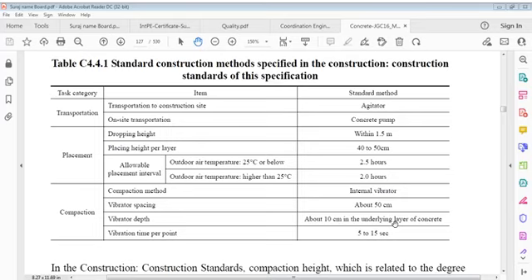Allowable placing interval: if outdoor air temperature is 25 degrees Celsius or below, it is 2.5 hours. Outdoor air temperature higher than 25 degrees Celsius, 2 hours. So if it is 25 or below, it is 2.5 hours, and if it is above 25 degrees Celsius, it is 2 hours. Compaction method: internal vibrator and vibrator spacing about 50 centimeters. Vibrator depth about 10 centimeter in underlying layer of concrete, meaning interlocking between two layers. Vibration time per point 5 to 15 seconds.